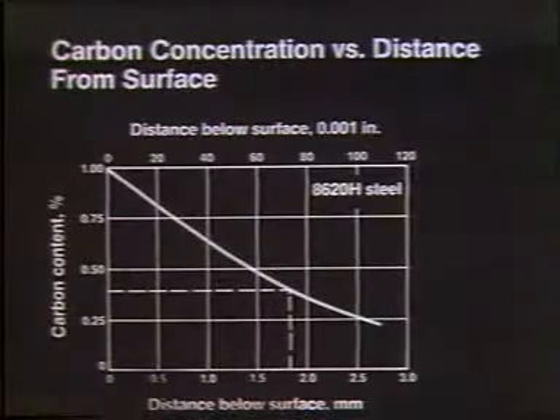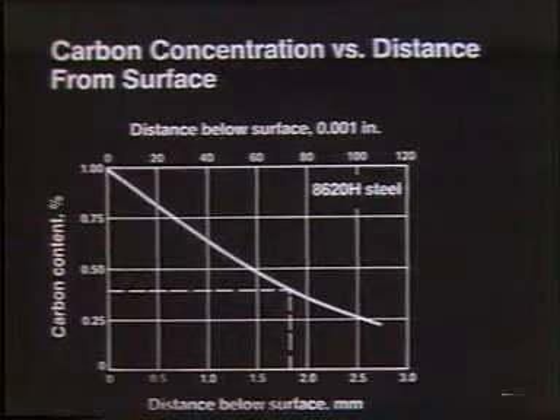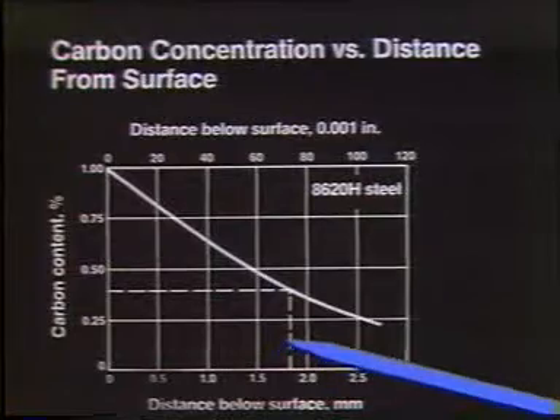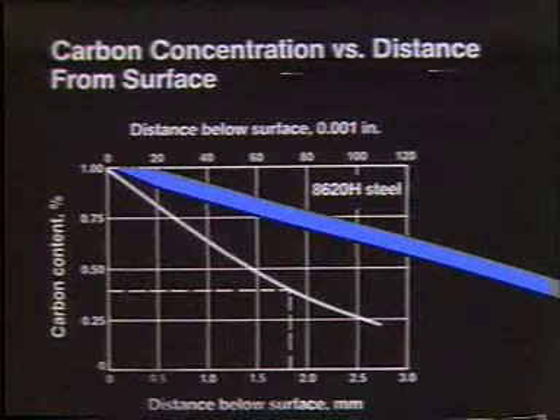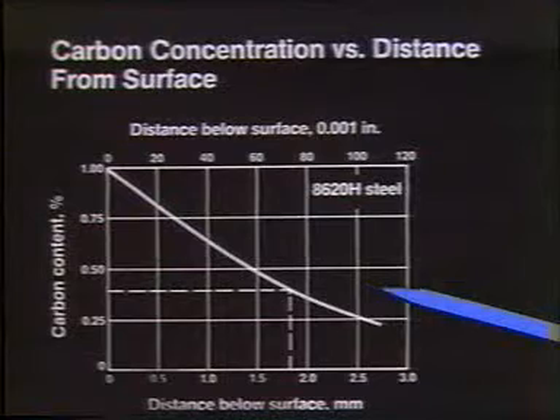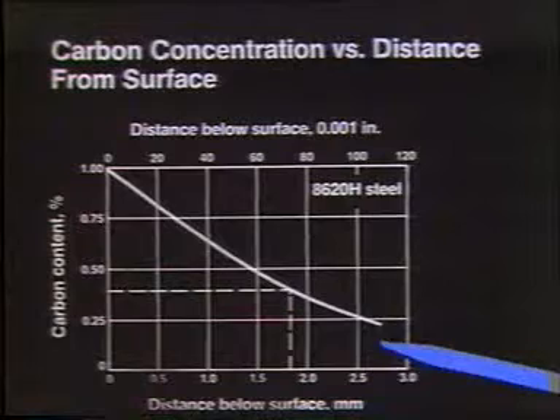So if we start inspecting some of the diffusion characteristics, we find that if we took a characteristic carbon concentration versus distance for a given steel, this is an 8620 steel, we're going to look to see how far below the surface the carbon content has changed, and we find that on the very top surface of the material we get a rather high carbon content, and it begins to drop off, and it drops off rather rapidly. So we don't penetrate the material too far. Actually, it goes down measured in thousandths of an inch, but that may be good enough for what we want to do.